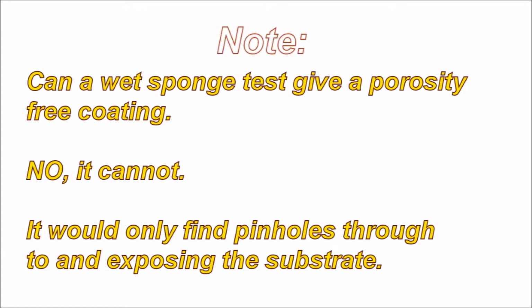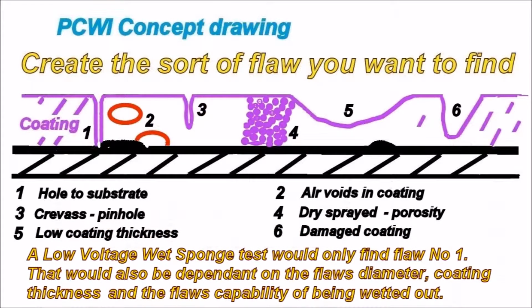Can a wet sponge test give a porosity free coating? No, it cannot. It would only find pinholes through to and exposing the substrate. A low voltage wet sponge test would only find flaw number 1. That would also be dependent on the flaw's diameter, coating thickness, and the flaw's capability of being wetted out. All the other flaws, a wet sponge unit will not find.